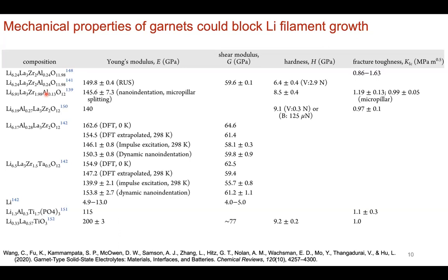Certainly these groups are good at doing all of the above, and of course all their papers go into way more detail than I can comment on as a non-expert in modeling. But you already see here that while these elastic moduli are calculated, they are specified as DFT at 0 Kelvin or extrapolated to, let's say, room temperature, right? So something that has a little bit more energy, you feed in some kBT, and now it's a value that resembles something at room temperature when the calculation is really done at 0 Kelvin. So useful, it still builds our understanding, but there are some limitations. And of course, we take that into consideration.